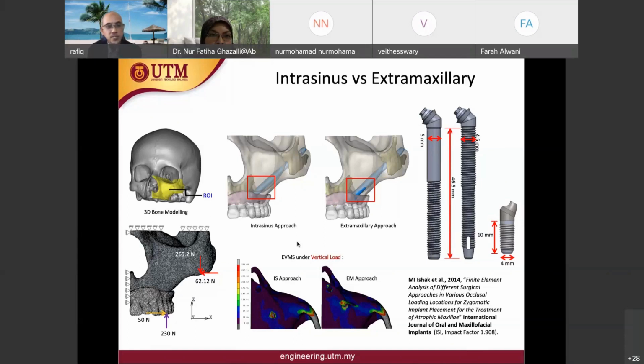We developed the 3-dimensional model of the skull, and we pick a certain ROI, and then we design the implant, and then we put the implant to simulate the 2 different approaches, the intrasinus and extramaxillary. We analyze using finite element with the loading as shown in the slide there, and then we look at the von Mises stress under vertical load. So we can see that the extramaxillary approach has more stresses underneath there, compared to the intrasinus.